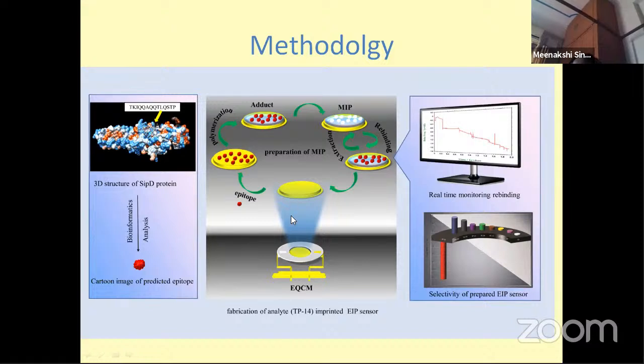So this is the electrode, this is the quartz crystal, and the gold film is deposited on the quartz crystal. This gold film will be treated with the epitope through the sulfur atom of the cysteine amino acid. These epitope peptide sequences will be self-assembled on this gold surface, and then the monomer 3-sulfopropyl methacrylate will be added, and the cross-linker will be added, and it will be polymerized on the electrode surface itself, because the technique is electropolymerization. I will show you the CV of the electropolymerization process, and this is called an adduct because this polymeric matrix has these template molecules, these protein epitope peptide molecules.